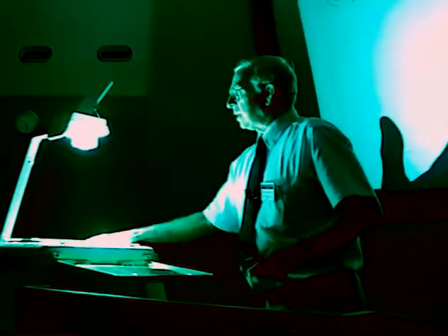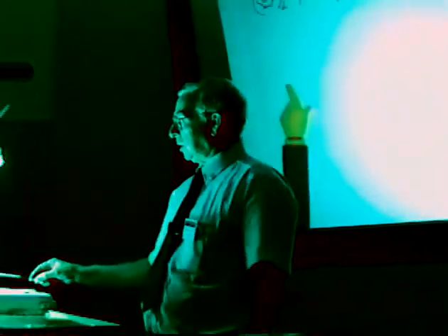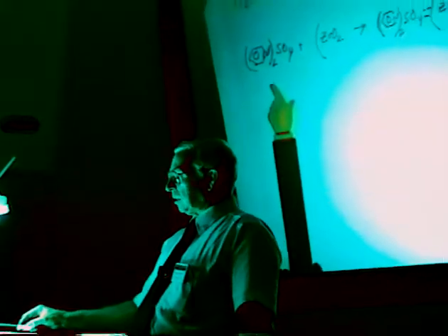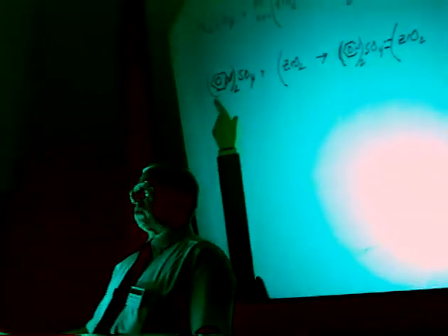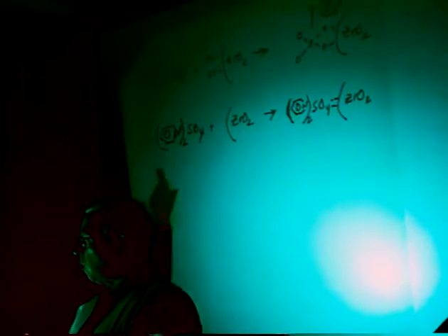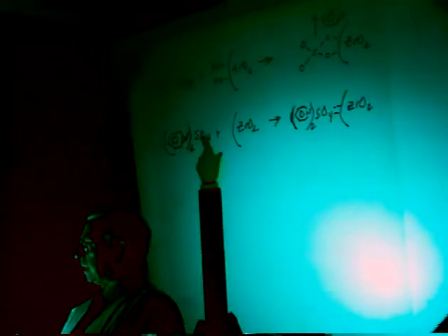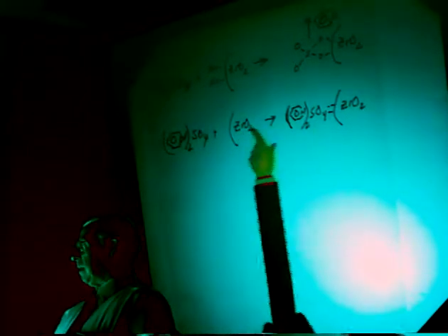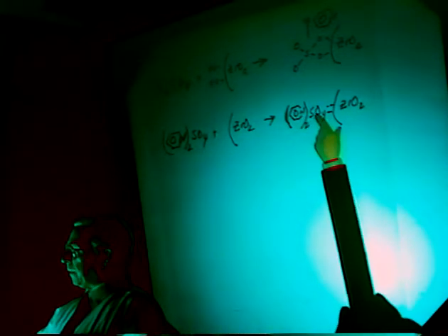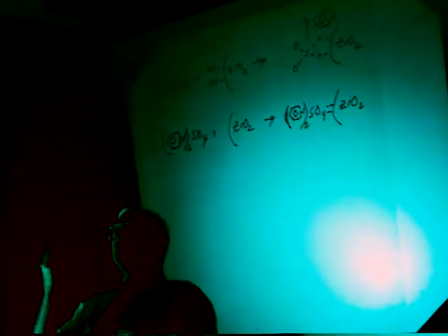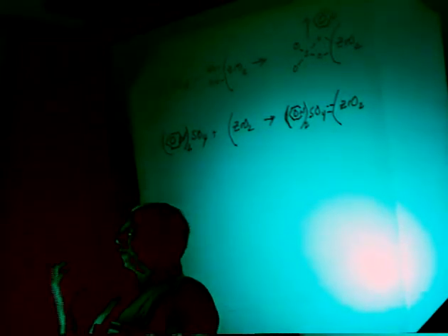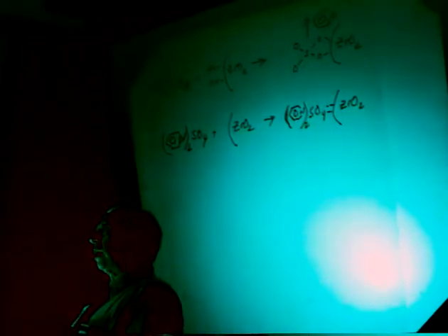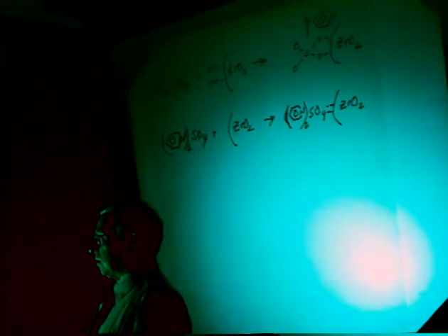Now, we carried this out to try to get involved in the debate, is it Bronsted or is it Lewis acidity? One way to determine acidity is to adsorb pyridine. So we preformed pyridinium sulfate and added this to the zirconium oxide. The preformed pyridinium sulfate is what you would expect to form if you chemisorb pyridine on a Bronsted acid site.